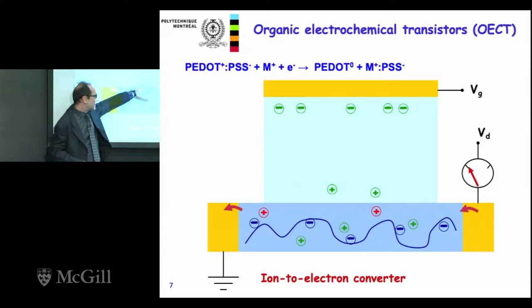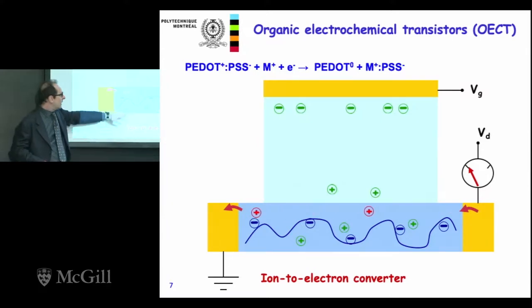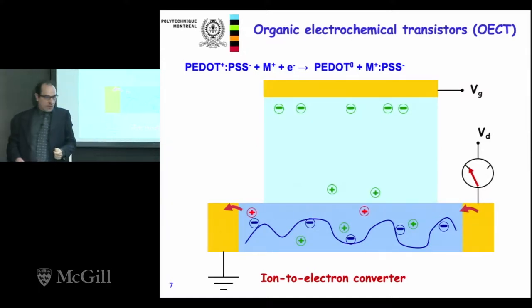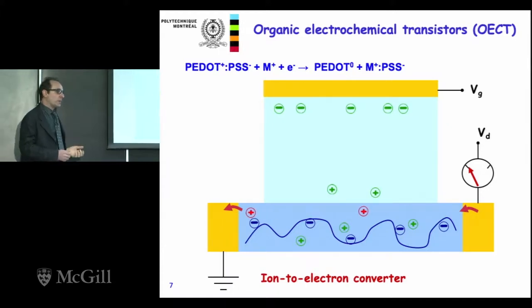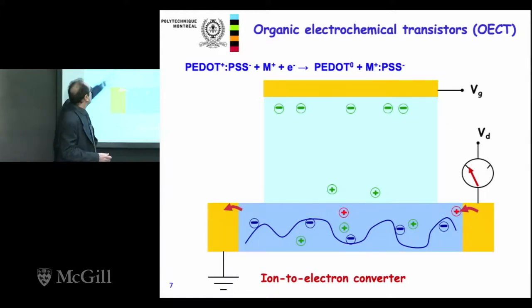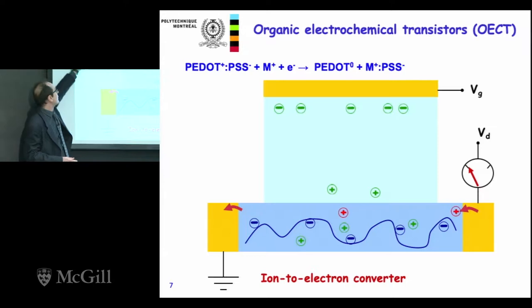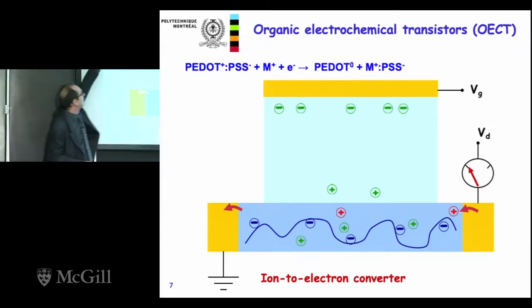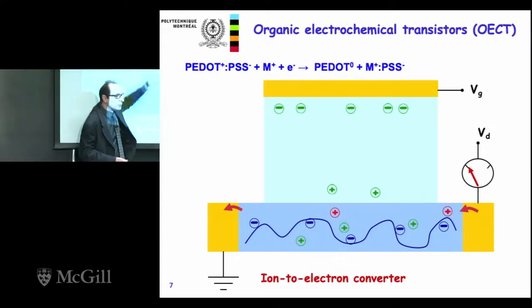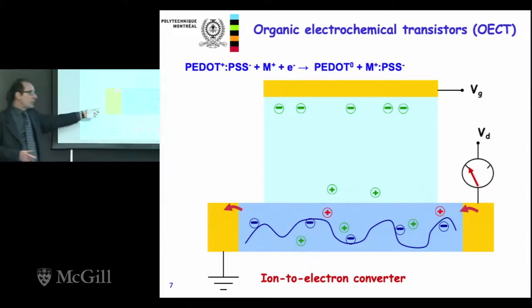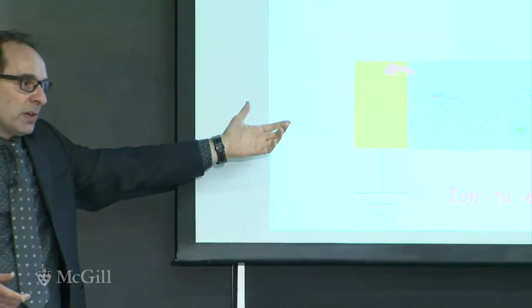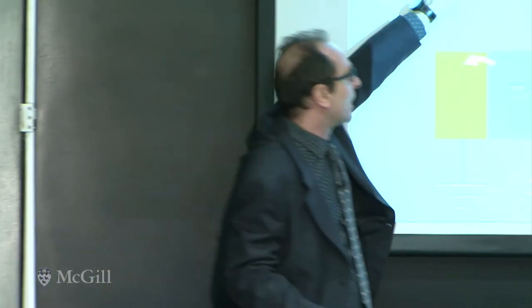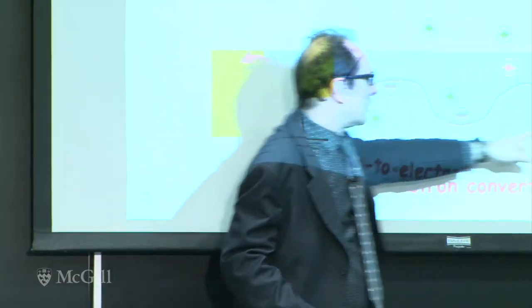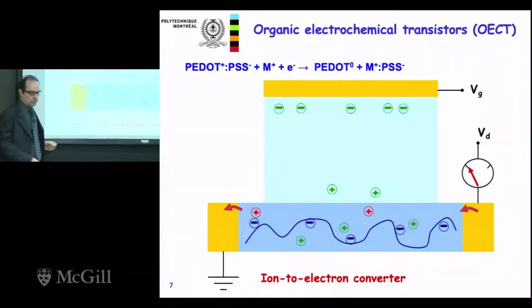What happens at this interface is that some ions go into the polymer and compensate some of the negative charges of the dopant. This is equivalent to saying that you have a redox process. You go from the oxidized state of the PEDOT to the neutral state, which is much less conductive. In this way, you decrease the conductivity of the polymer and you also modulate the current, so you obtain a transistor effect. You use the voltage applied to this electrode to control the charge flowing between these two.